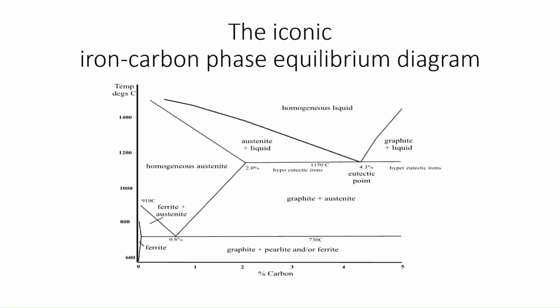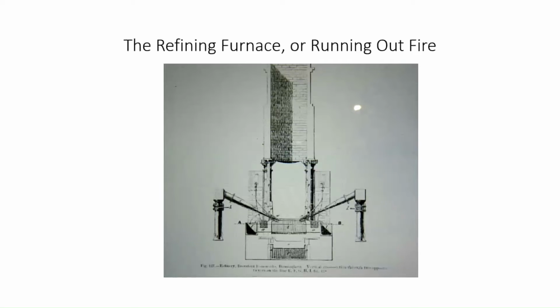When they tried to do what Henry Cort did in Portsmouth, in the areas where they had coke-fired iron, it was very difficult to make it work. So what did they do? They reverted to the running out fire. And they turned the iron from a grey iron to a white iron in just the same way that Wright and Jessop had converted their iron into suitable charge for their crucibles. And actually, that wasn't the only use of the running out fire, because it had also been used in that interregnum I spoke of, where they still had to use charcoal, but if they used the running out fire before they put it in the charcoal finery, then they could actually make significant economies.